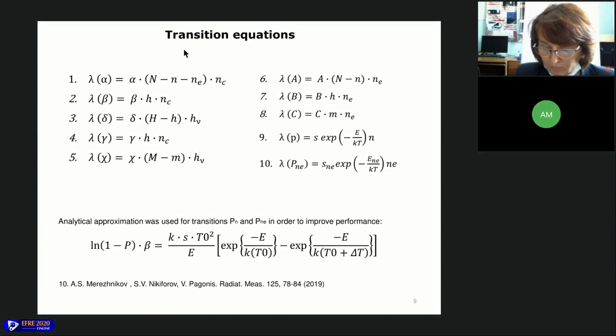Here you can see the probability equation for each transition. Generally, each probability coefficient is defined by level occupancies and some coefficients which are determined by physical properties of defects. One should determine the upper limit of the exponential integral for thermostimulated transitions. Since it cannot be expressed with elementary functions, an estimation of the integral was used.